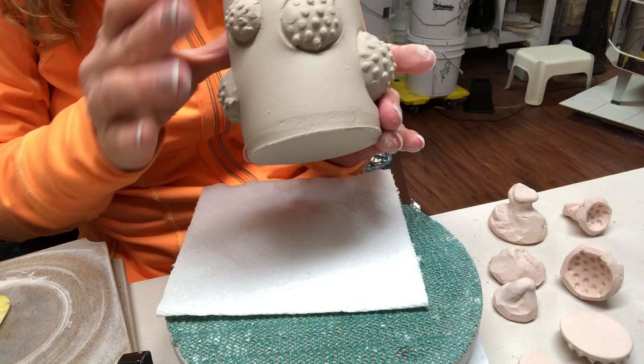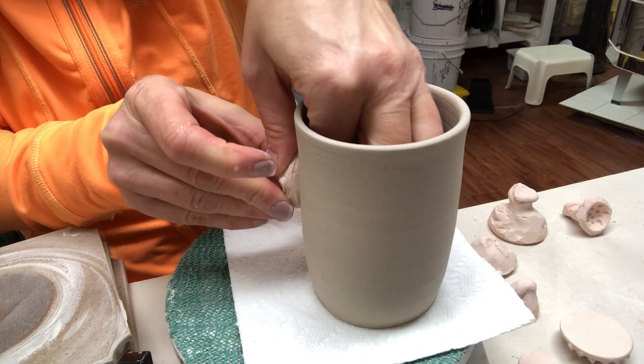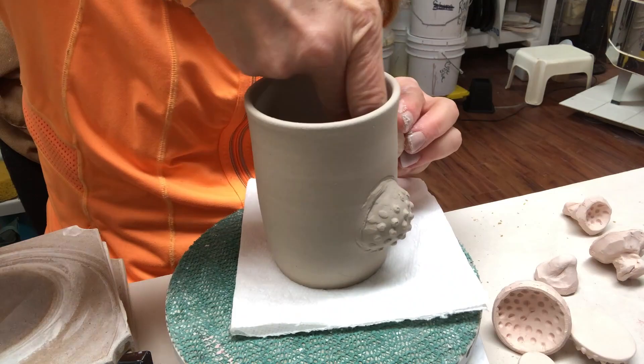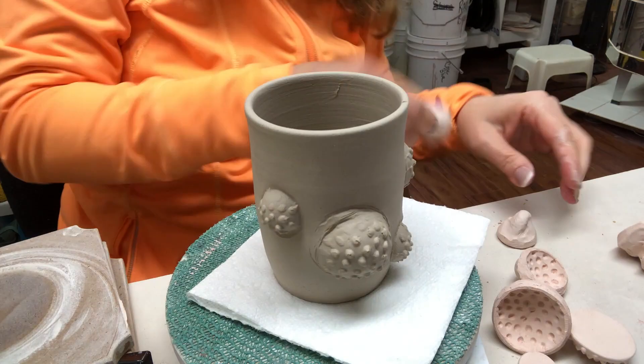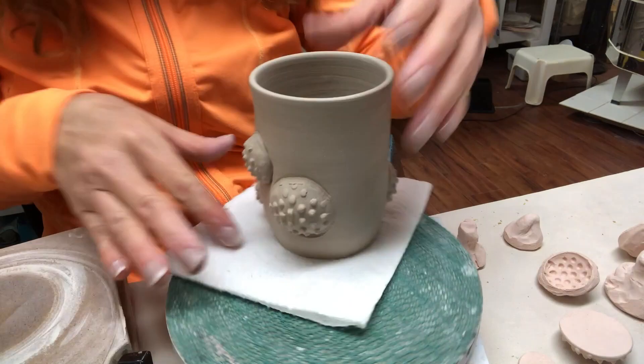In my case I did get a couple of rips when making some of them. You can see on the inside where it's dented — the indents are there on the interior of the wall. The clay must still be in that plastic stage; it's a stiff plastic but it still needs the plasticity to push out and go into the mold. I tried not to move the mold because I didn't want a shadow of where the little slip-trail bumps made a shadow line.